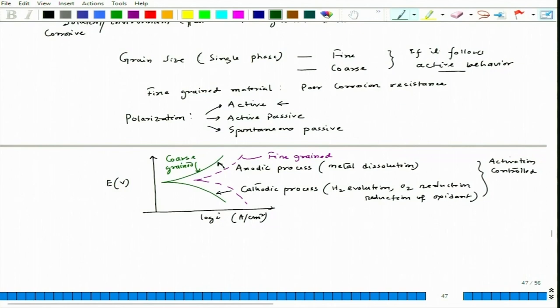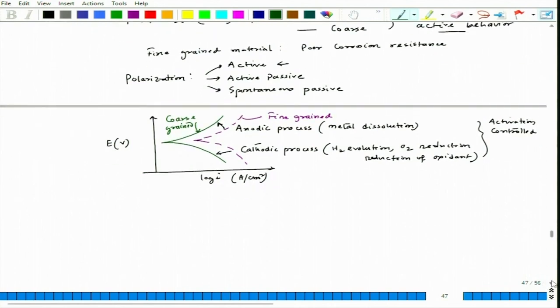Now why does it happen like that? There could be a possibility of higher attack in the case of fine grain, and that is why this polarization line is moving towards the right. And the corresponding corrosion rate, how do we measure? We just do a Tafel extrapolation, and this is my corrosion rate, I cor. Similarly, we do it for this case, where we do Tafel extrapolation, and then we find this is I cor for the finer one. We could see there is a huge increase in corrosion rate if it is fine.